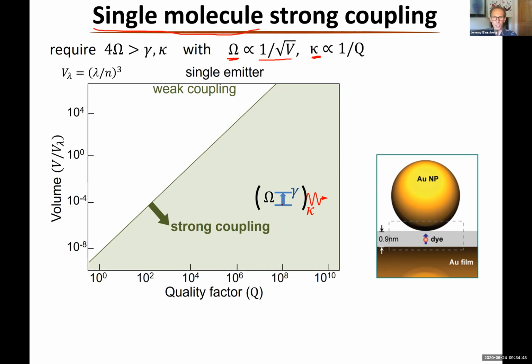So essentially what we have is this two-level system here, and if the light matter coupling is strong enough, then these levels split into two. So I get these two polaritons in the system, and I have to make sure that this coupling is stronger than either the losses, the dephasing of the two-level system, or the losses from the optical cavity. So you can plot the conditions for that on a graph of the volume against the quality factor. So you get a nice graph like this. And the strong coupling condition is this green line that I've shown there. And you also can look at the Purcell effect, which is how much you're enhancing the emission rate, which we'll come back to as well.